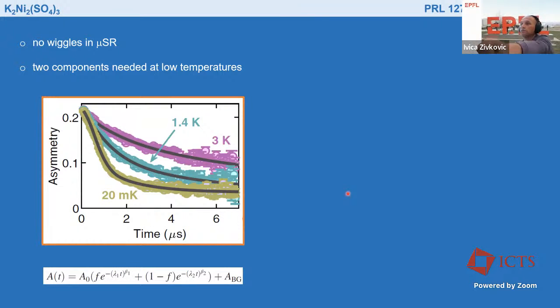Okay, and one of the most relevant features from an experimental point of view is the investigation of μSR behavior, where typically this is a go no go test of whether the system is ordered or not ordered, where the ordering typically shows up as wiggles in μSR. Here there are no wiggles, but the behavior at low temperature is rather non-trivial, where you need to use two components, and given that there are not many features in these curves, the modeling of that is not really unique.